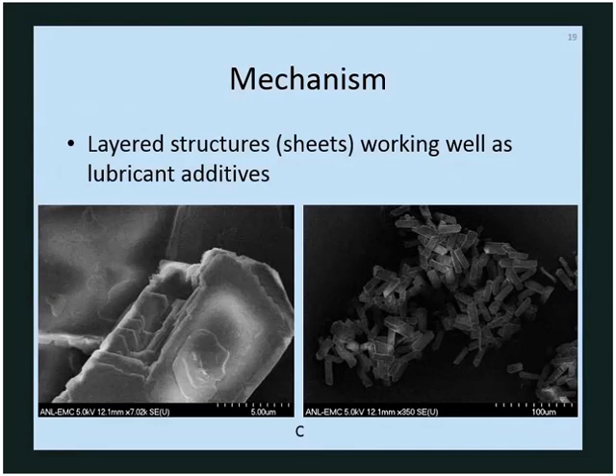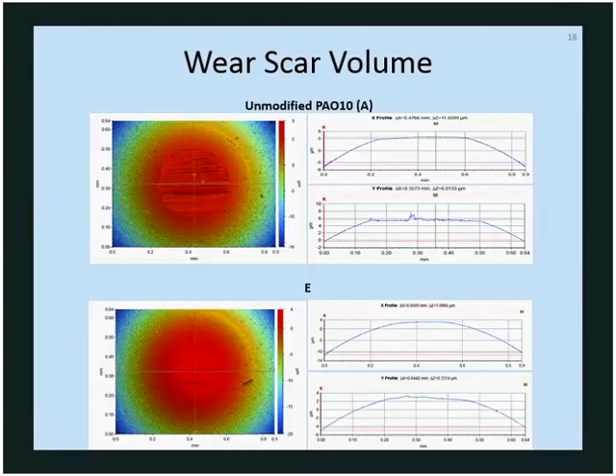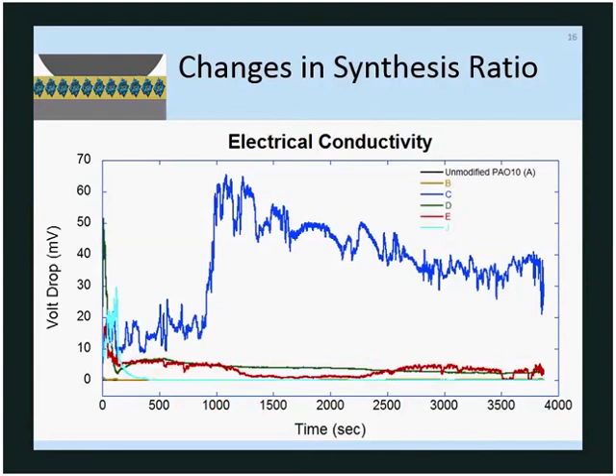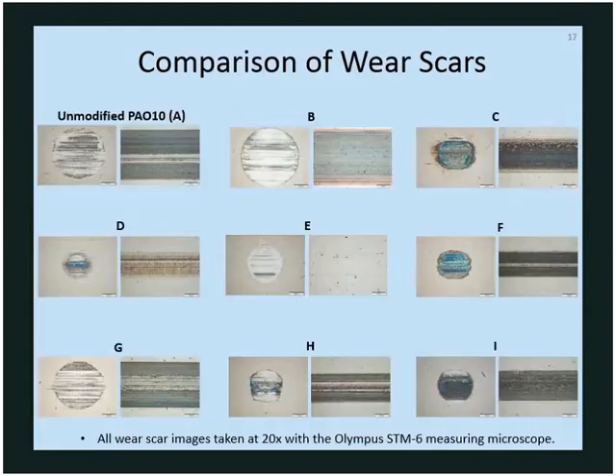And I had one quick question. On the conductivity test, you said the layer should insulate more, but with the additives, you might have been adding ions to the solution by using acids or bases, and that would affect conductivity too, wouldn't it? Yeah, there's a lot that goes into that. There's a lot more than just saying that this exhibits a tribochemical film layer. There are a lot more tests that have to be done, and also looking at the actual flat, you can do another analysis and see if actual residue on the flat indicates that. So it's possible you still have a layer and the conductivity doesn't suffer that much.